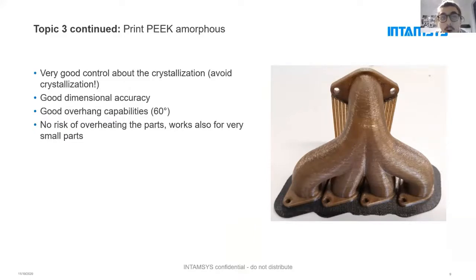Why? Again, you have a very good control over the crystallization. That means you avoid the crystallization, which allows you still in the end to get a crystalline part, but if you then anneal it, so tempering or post-treatment, then you have an equally crystallized part. Overall, amorphous printing gives you a very good dimensional accuracy, so we speak about plus minus 200 micron. You have very good overhang capabilities, you can handle overhangs up to 60 degrees, and you have no risk of overheating parts. Even with very small nozzles on small parts, you get very good detailed results. In the end, related to FFF-based technologies, printing with a 0.25 millimeter nozzle, a detailed object in 1 by 1 by 1 centimeter is already very hard, related to the technology itself.